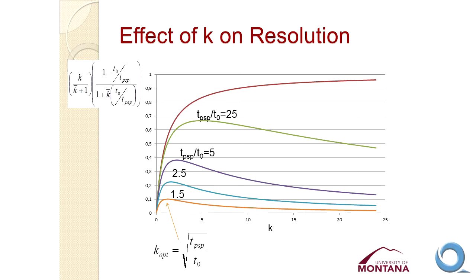The red line is what we see for conventional chromatography where we have a true stationary phase. So as we increase the retention factor, we see a sharp increase initially in resolution, and then it kind of levels off after that. With electrokinetic chromatography, we see that same sharp increase, but then we actually lose resolution as compounds are more retained. So the take-home message from this set of plots is that, first of all, electrokinetic chromatography is always at a bit of a disadvantage in terms of these terms relative to conventional chromatography. So to overcome that and still achieve high resolution, we need to have high theoretical plate counts and good selectivity.